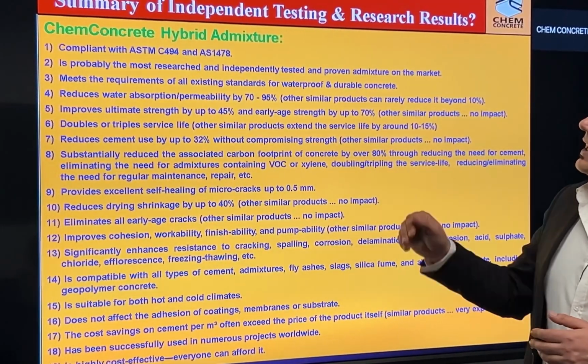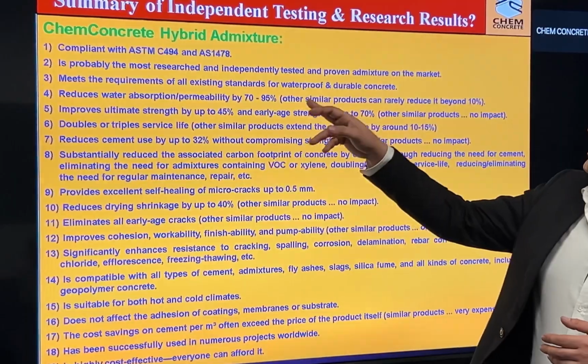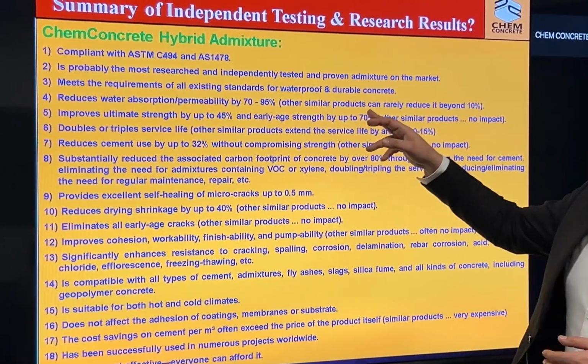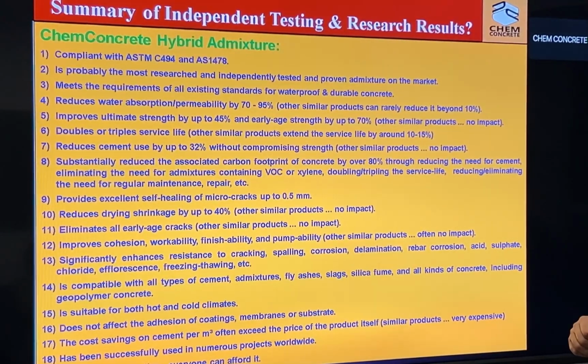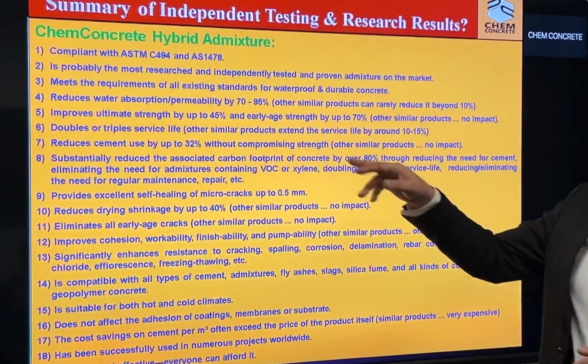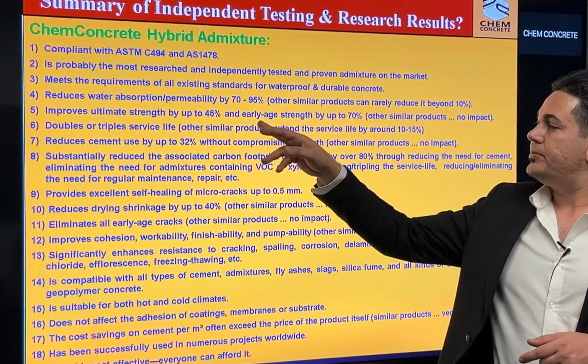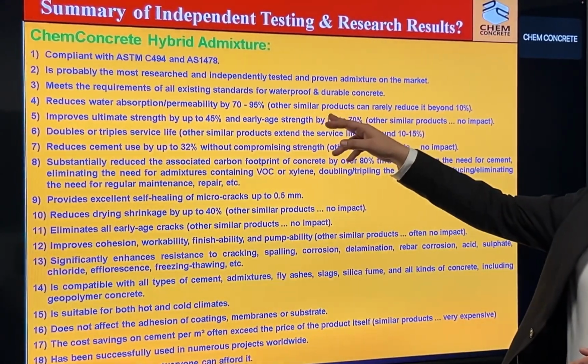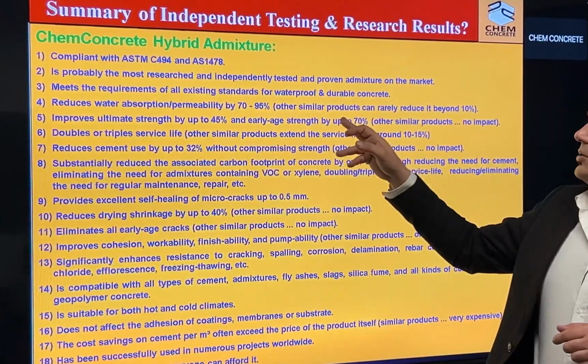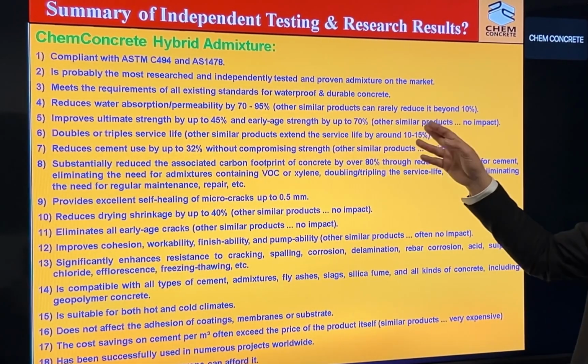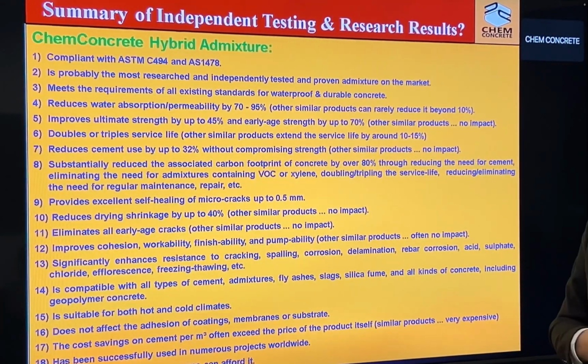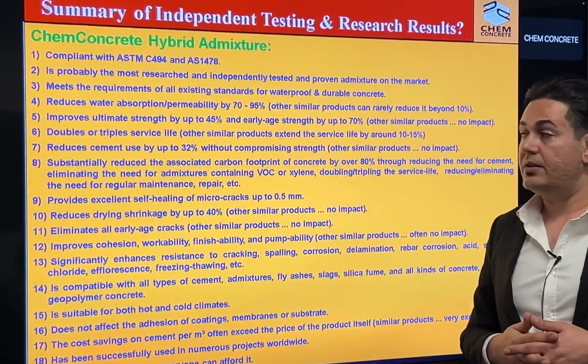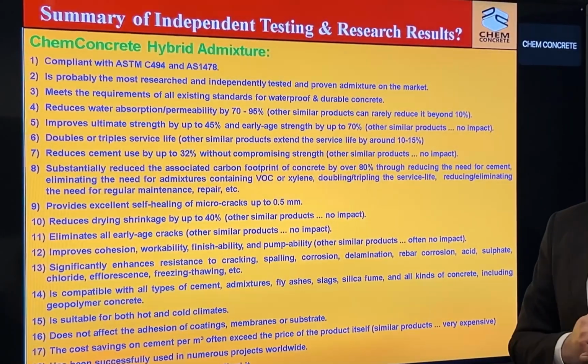The next one is that the product meets the requirements of all the existing standards for waterproof and durable concrete, and it reduces water absorption and permeability by 70 to 95% depending on the dosage used. This is why other similar products can rarely reduce it beyond 10%. And it also improves the ultimate strength of concrete by 45%.